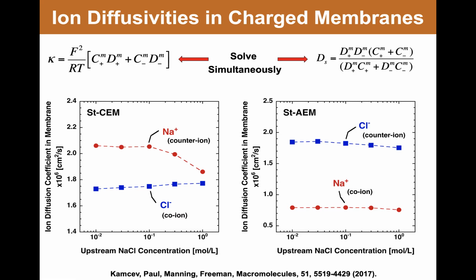You wouldn't see this kind of differentiation where the counterions are moving faster than the coions. And so this prompts us to think back to the Manning picture, where the ions are partitioned into two different populations, one that is condensed and relegated to stay relatively close to the polymer backbone, and another where the ions that are farther away diffuse more or less like any other ions.